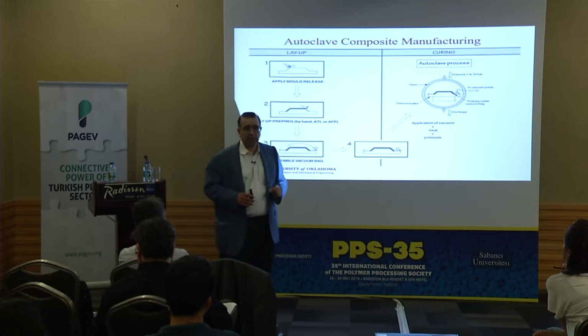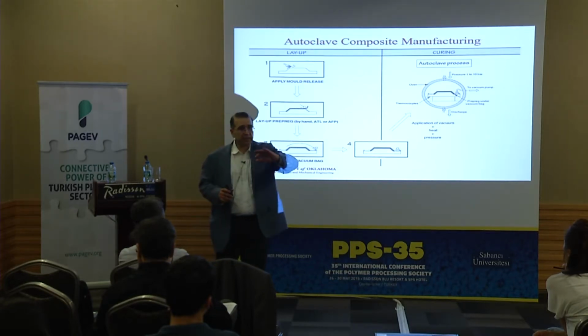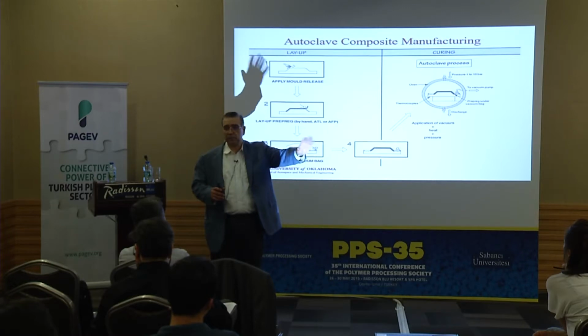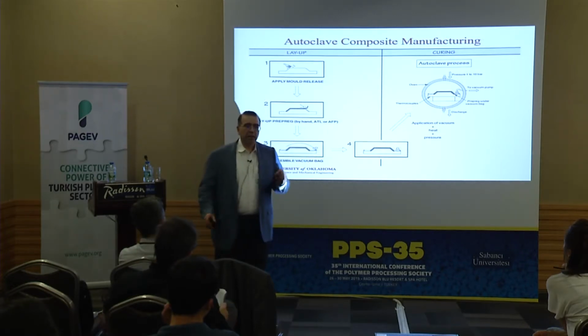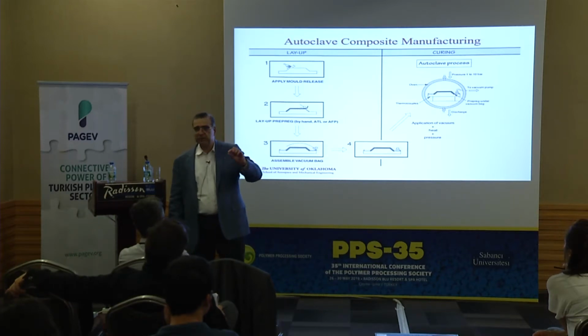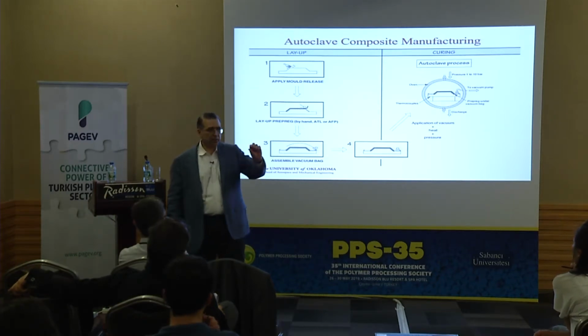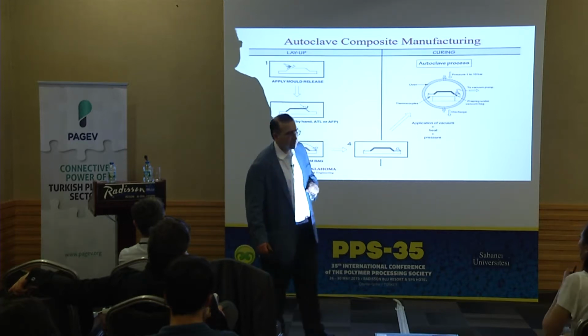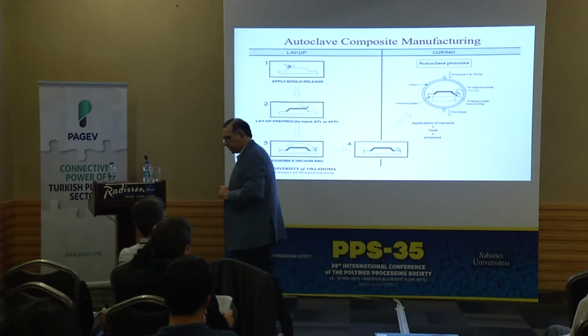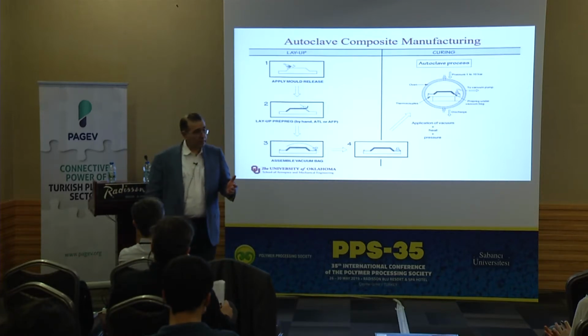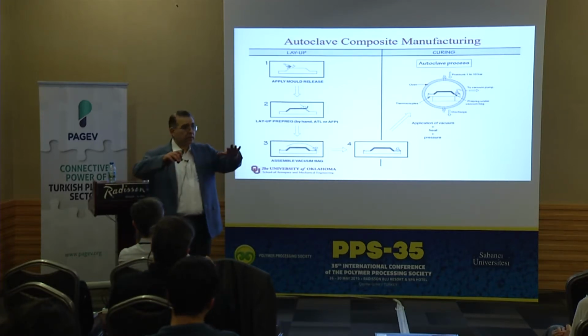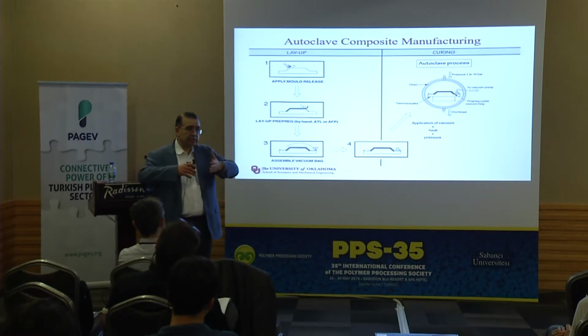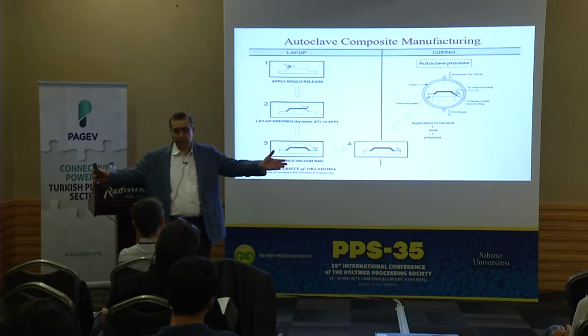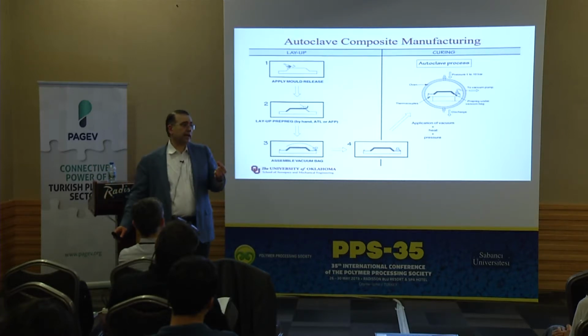So can you make the part without applying the pressure? Yes. You can essentially follow the same temperature profile without the pressure, and you will have a part. The part you made in the oven will be a little bit thicker, 25% thicker. Why? Because of not having pressure, resin is not pressurized and it didn't really flow out. The only thing that makes the resin flow out in oven cure is the vacuum pressure, right?